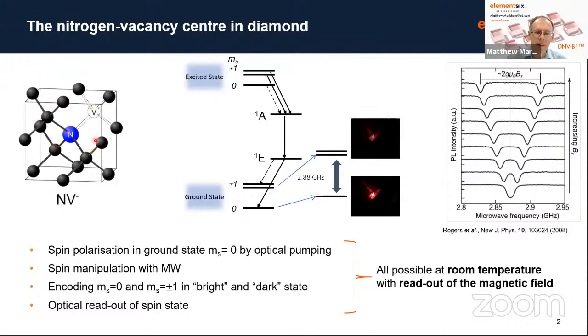And the NV defect can exist along 4 different axes, so you typically have 8 pairs of lines within a system, because you have NV defects along all 4 different orientations. What's particularly unique about diamond is it does this at room temperature. Most other quantum materials, if you like, you'd have to cool down to liquid nitrogen or liquid helium temperatures to see these sorts of effects, but because of the unique properties of diamond, you're able to see these at room temperature.